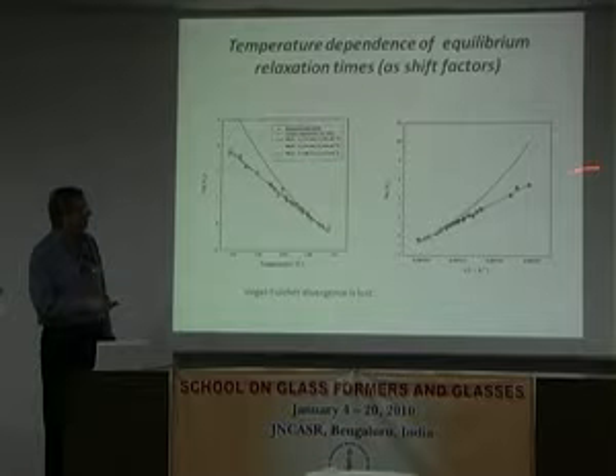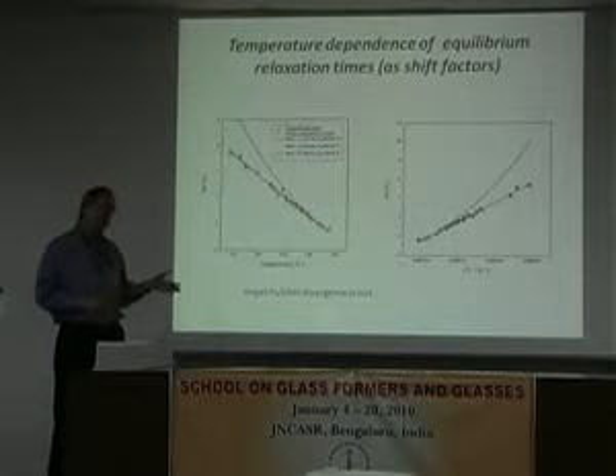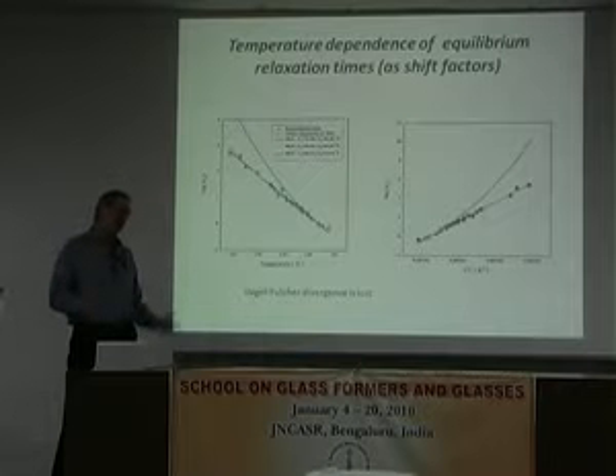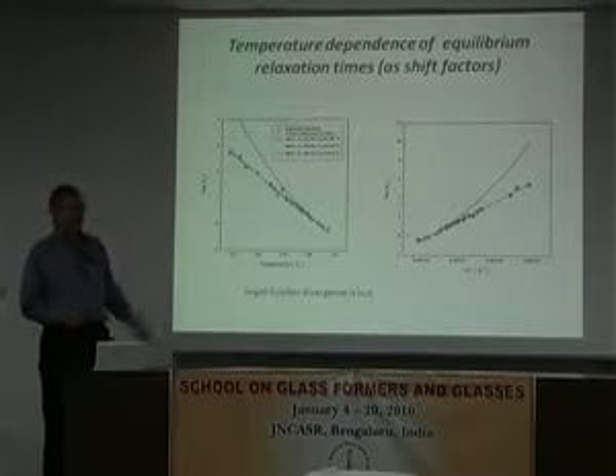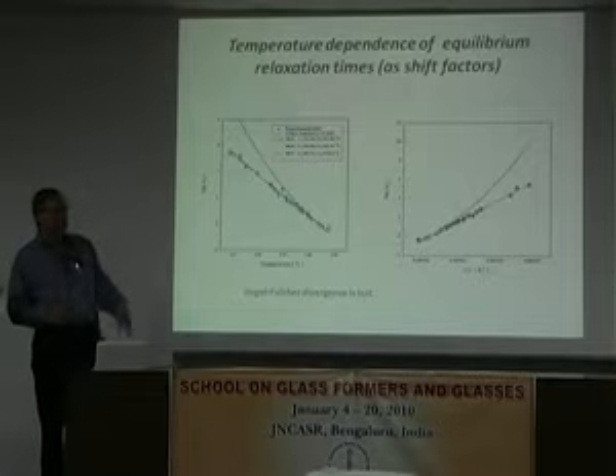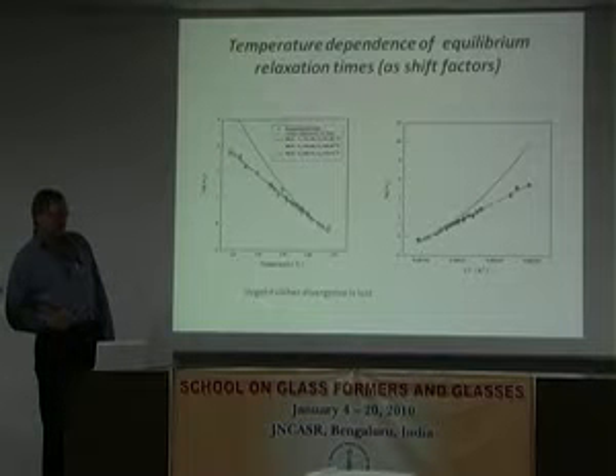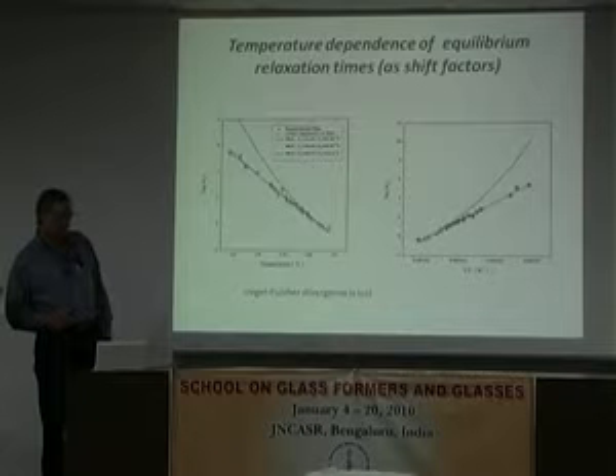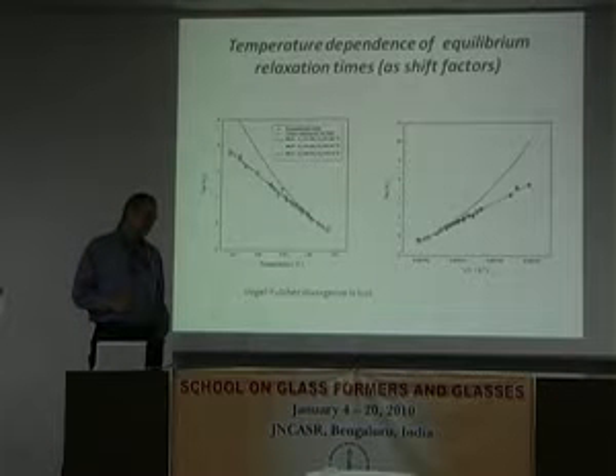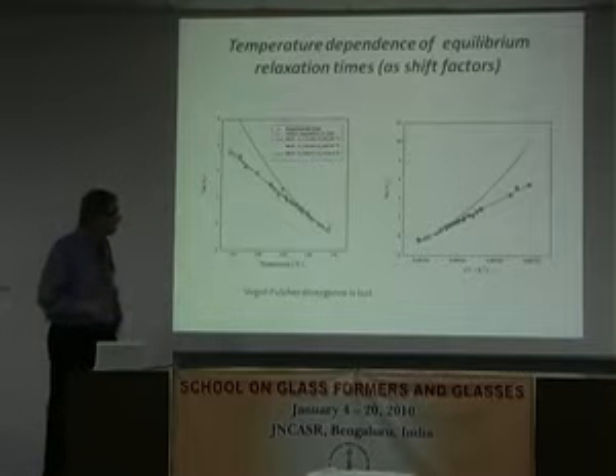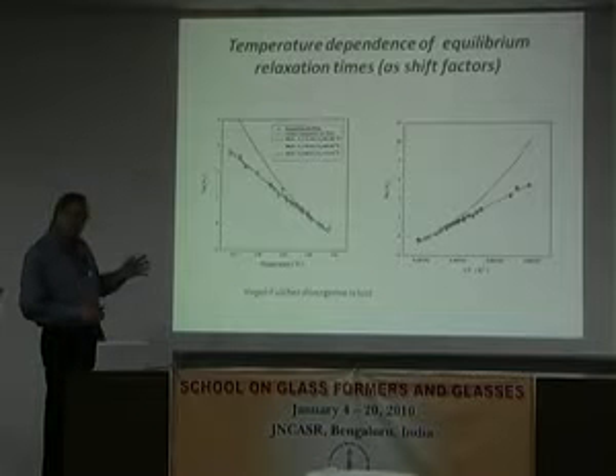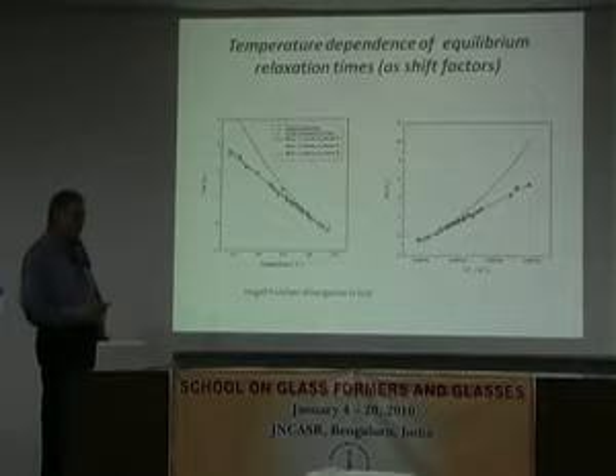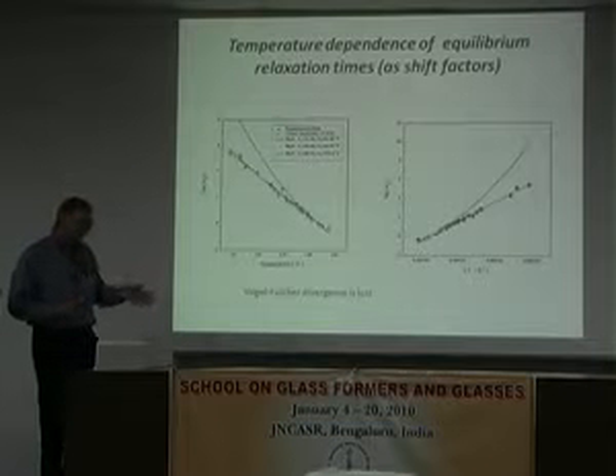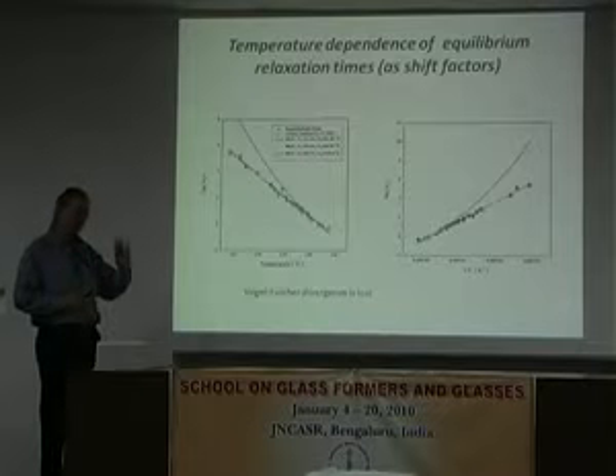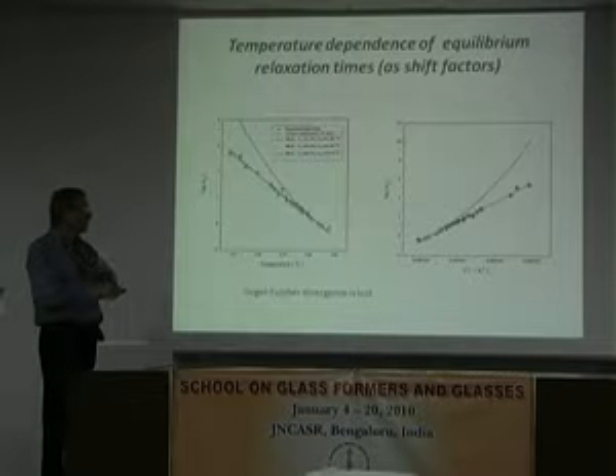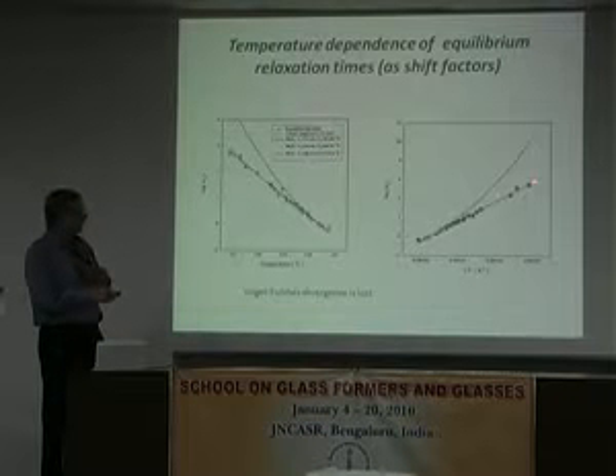But apparently in this temperature regime, we're falling off of that divergence. So we have this non-diverging behavior that he talks about more recently in his Nature Physics paper. But do you have cases where the Vogel-Fulcher continues to be valid, and then what do you expect to see? If the Vogel-Fulcher continued to be valid, and Rancko Richert claims that for polyvinyl acetate that's the case, so there may be some subtle events that have to do with when this is going to take place. But in that case, this would come up to here.